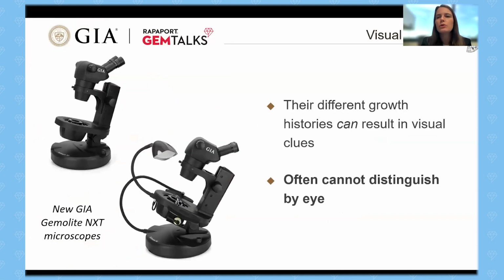Now, in the past, visual clues would have been very, very easy. You can potentially use a microscope to differentiate the growth history because it could potentially incorporate certain inclusions that you could identify by using a microscope. And this was certainly the case for the first materials. However, now, in particular, with the higher clarity goods that we're observing, you often can't distinguish them by eye.